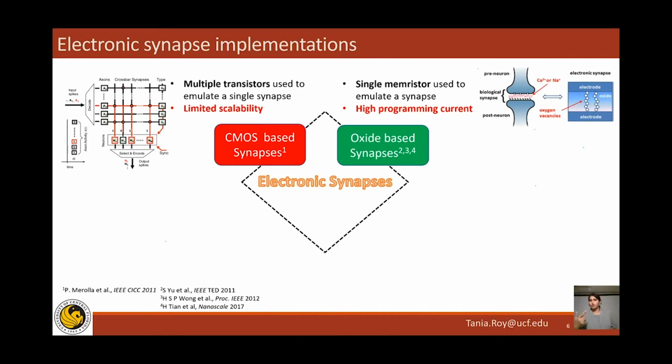So that was showing switching because of temporary breakdown. And one was able to demonstrate multi-bit memory as well, resistive random access memory. It started with that. Then people started to also realize analog memory with these memristors. So then really good synapses started to be demonstrated. And yes, a lot of papers still today exist based on these oxide-based synapses.